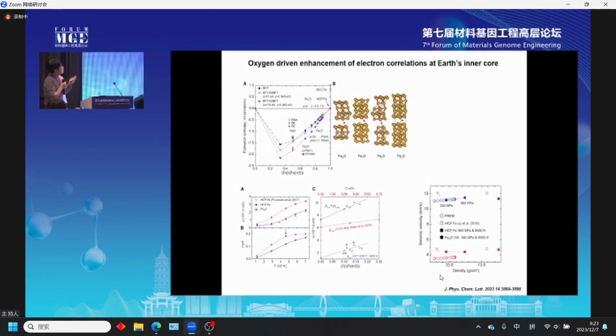And this is one additional paper we published. We used dynamical mean-field theory. Why I'm showing this one: it looks like a quite simple crystal structure prediction, like a convex hull graph between pure iron and pure oxygen. So this is a binary structural prediction, which seems quite simple.